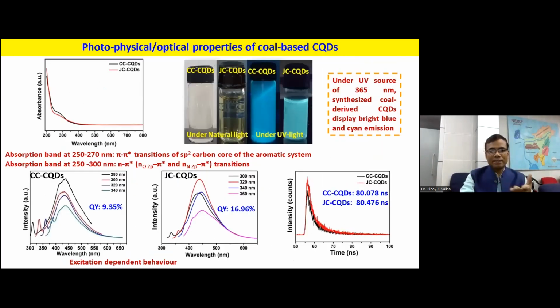And then we also studied, in the absorption spectroscopy, we found that, as you have seen in the FTIR and XPS studies, there are carbon-carbon double bonds and carbon-oxygen double and single bonds. So in that, the pi to pi star transitions are giving the blue emission, around 400 to 480 nm.